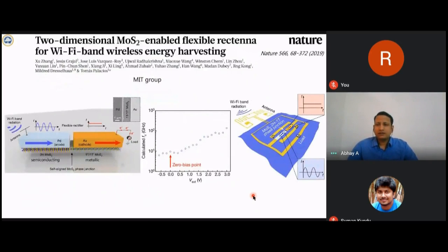So in January 2019, a group of researchers from MIT, USA, published a very new idea of fabricating these Schottky diodes with the two-dimensional material MoS2, which has two polymorphs. One is metallic and the other one is semiconducting. You can see this is the metallic part of MoS2, indicated here as 1T, and the 2H form of MoS2 is semiconducting.